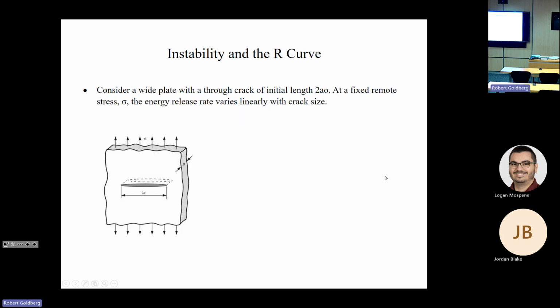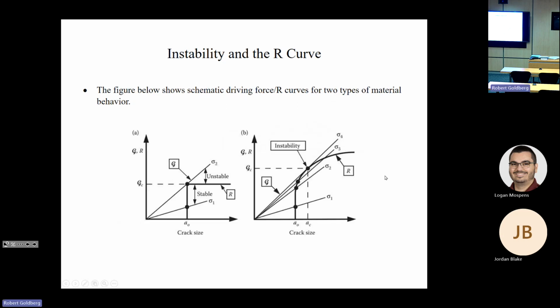So we'll start off by considering our wide plate with a through crack of initial length 2a sub 0 and at a fixed remote stress sigma, the energy release rate varies linearly with crack size. So we developed this before. Our energy release rate is equal to pi times the square of the stress times our half crack length divided by the modulus. And this figure shows the R curves for two types of material behavior.